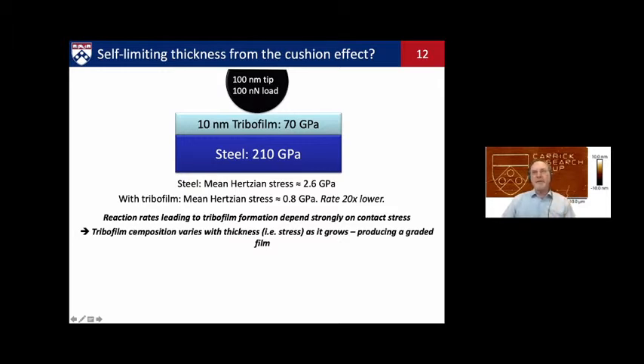We think it also is behind the change in composition of the tribofilm as it grows. As you go through the thickness of the film, we know that its composition is changing. And we think that's related to the fact that the stress is different at different thicknesses, leading to different pathways or different degrees of completion of the chemical processes that occur during the sliding. There's been some nice modeling from Rob Bozeman's group showing that the results we get can be plugged into a kinetic model.